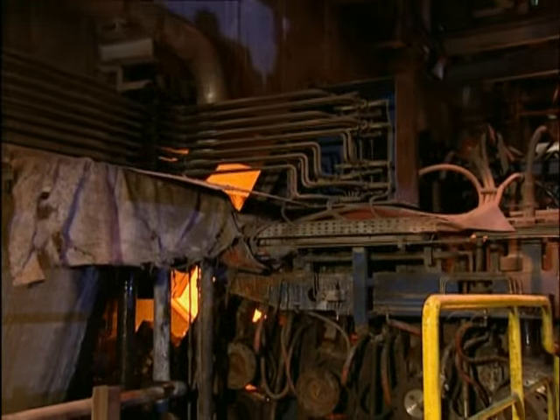A development based on tailored blanks are tailored tubes — tubes of different material thickness being produced here as prototypes on a tube welding line. Tubes like this allow a completely new approach to body engineering. Developers hope to achieve weight reductions of up to 30%, moving steel into weight classes previously reserved for alternative, more expensive materials. The hydroforming process is used to form the tubes into complex shapes: a mould encases the tube, water is fed in from both ends at high pressure, expanding the material and pressing the steel from the inside into the mould. Processes like this can save auto manufacturers from having to produce and process several individual parts.